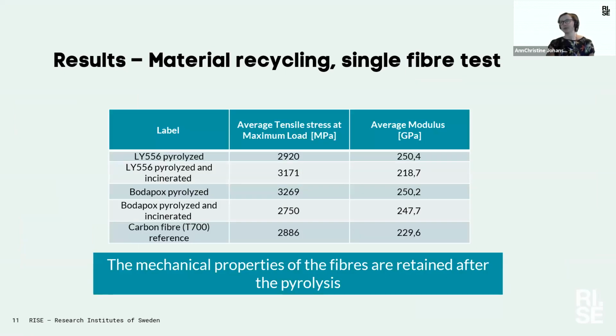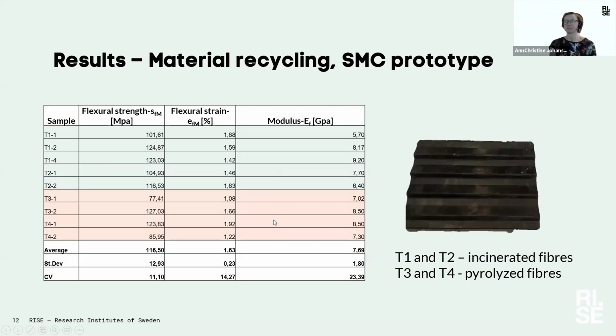We have also characterized the fibers, and as it seems, the mechanical properties are more or less retained after the pyrolysis process. Here we have a carbon fiber reference, and we have tested the strength and modulus, and then we have compared that to the pyrolyzed and incinerated fibers, and it's more or less in the same range at least.